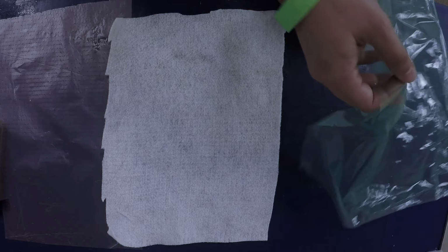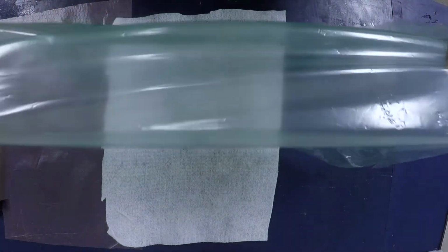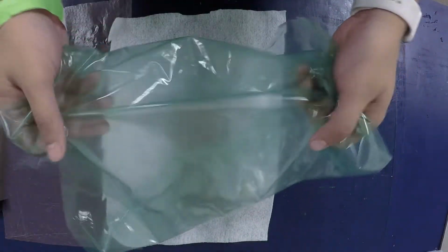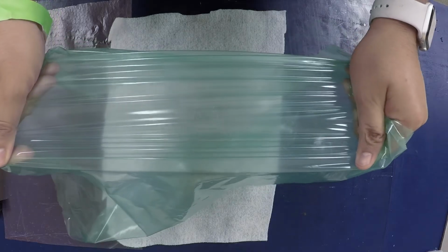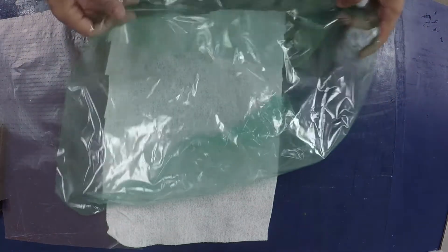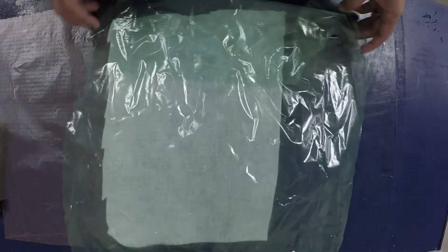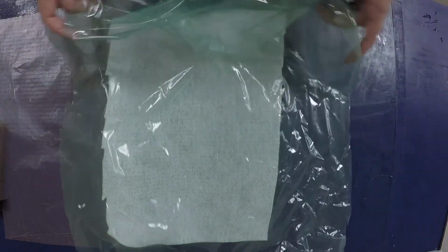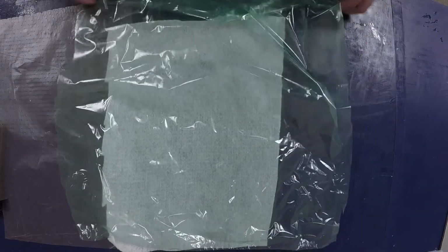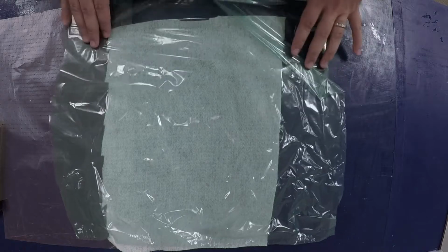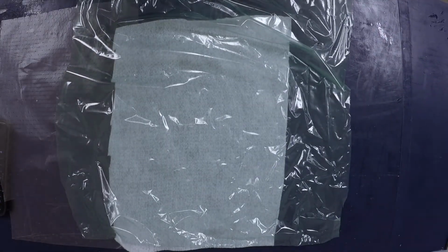Finally, the last material is the vacuum bag. The vacuum bag is the barrier that allows a seal to be formed with the sealant tape. It is always recommended to have an oversized vacuum bag to allow for any unforeseen deformations that could cause a fitted size to no longer reach the other side of the mold. Just like the release film, there are various types of vacuum bags that allow them to adapt to the project they are being used on.